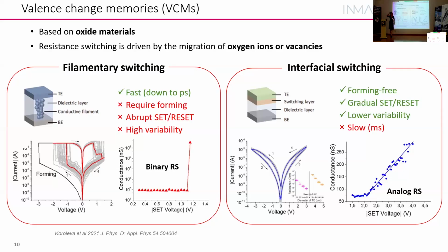So here we do not create a filament. What we do is to move the oxygen vacancies close or far, or more or less, towards one of the interfaces. And then normally these memories operate from the beginning. We don't need these forming steps.